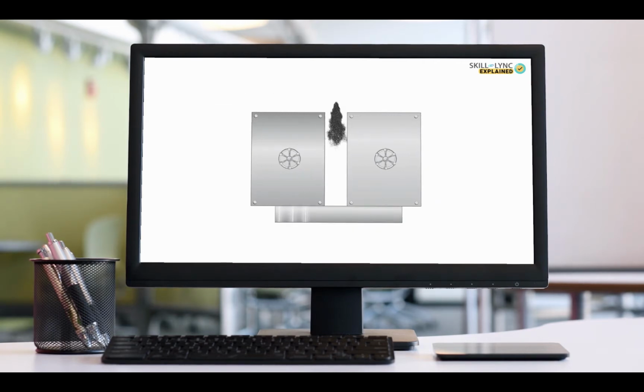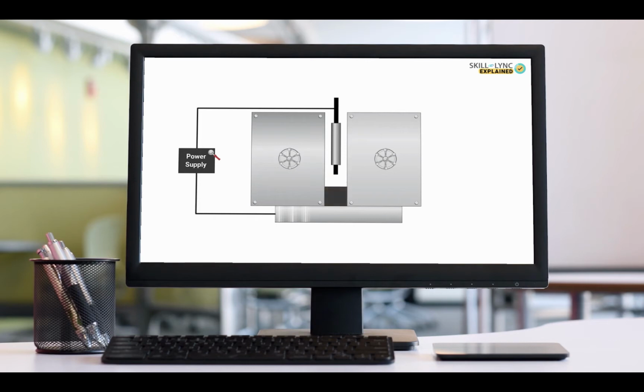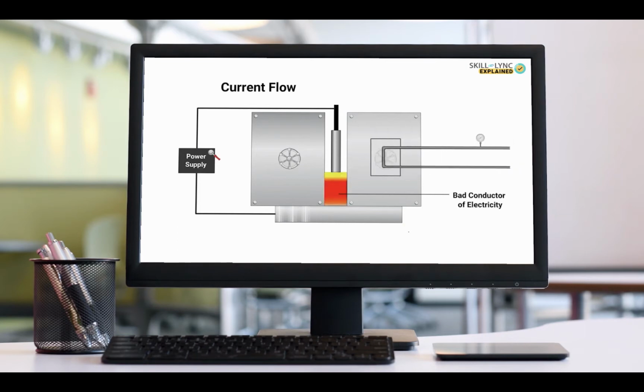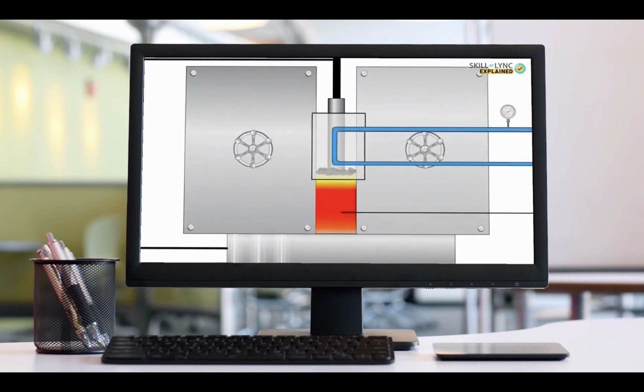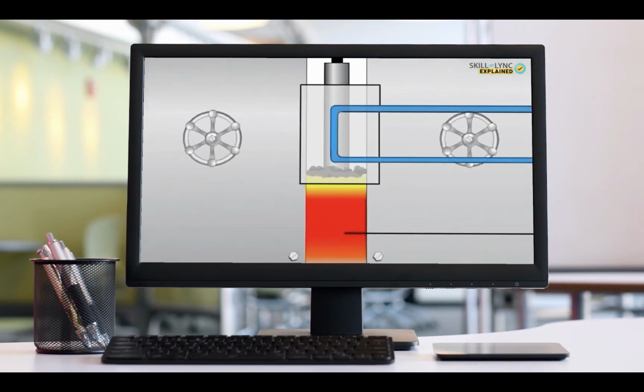Since this procedure does not purely depend on arc generation, it is commonly not considered an arc welding procedure. Instead, it is considered a fusion welding process. The mold which is used to hold the entire weld pool is normally water-cooled. Since the density of the slag material is much lesser than the molten electrode material, it stays on top of